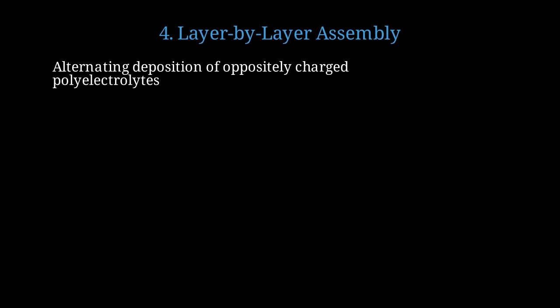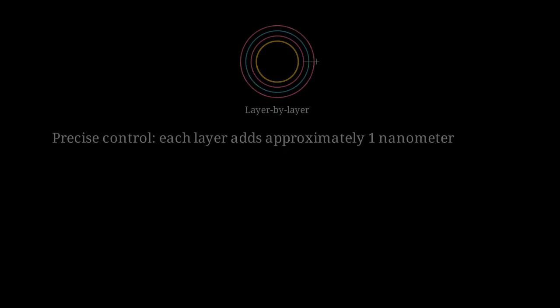Another powerful technique is layer-by-layer assembly, building shells one molecular layer at a time. We alternate deposition of positively and negatively charged polymers, building up layers through electrostatic attraction. Each layer adds about 1 nanometer of thickness, allowing precise control over shell properties and permeability. This technique gives nanometer scale precision in shell thickness and composition.